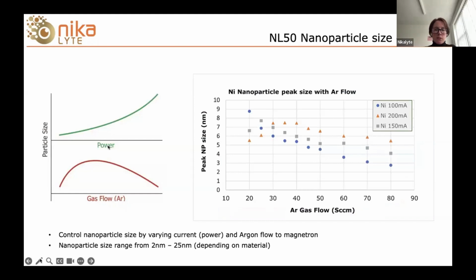So on the left-hand side here, I've got a bit of a schematic showing the relationship between the particle size and the power or the current on the magnetron and the gas flow to the magnetron. You can see that as you increase the power, generally the size increases. For the argon flow, there's a peak where the nanoparticle size is largest and then it starts to decrease again. I won't go into too much detail about why that's the case, but rather focus on some data here, which was measured for nickel nanoparticles.